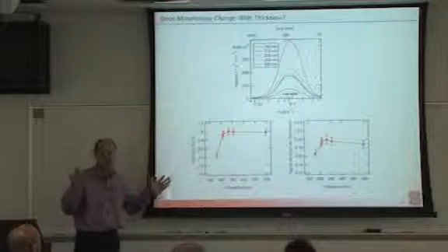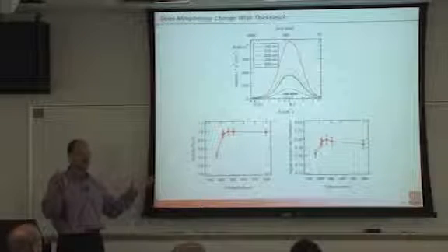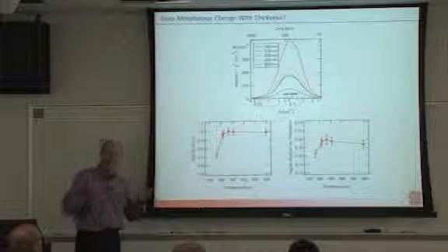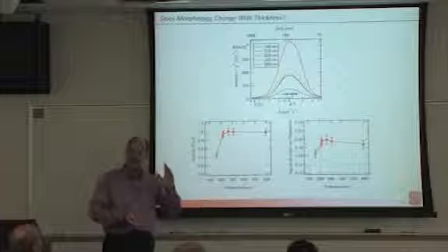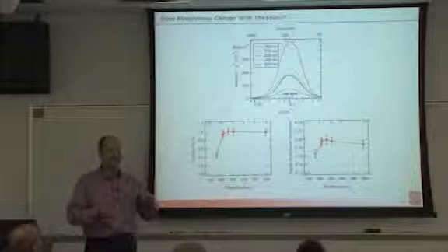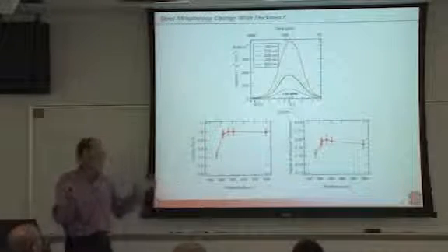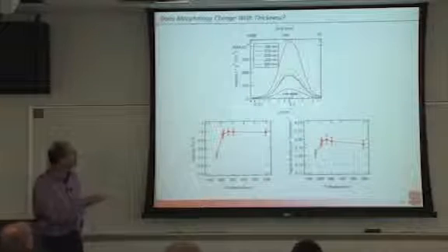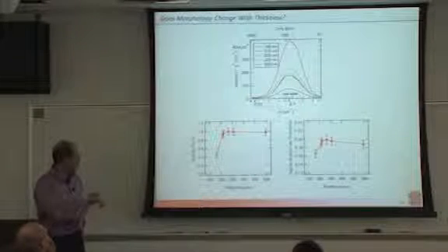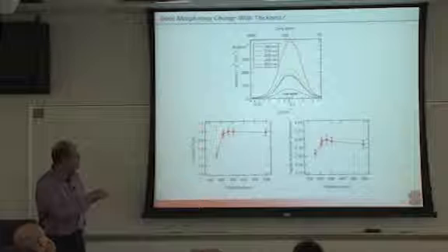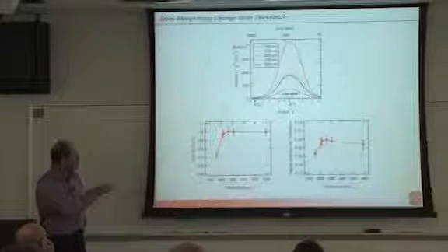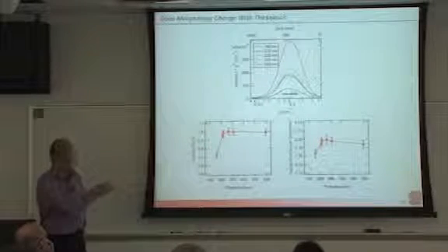It's the same, I should say. It's the same as a function of thickness. So very often that's not the case. The thicker films dry slower, they solidify differently, and the domain size changes. Here it doesn't.